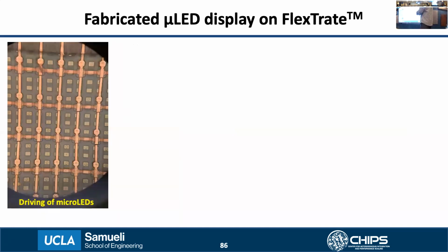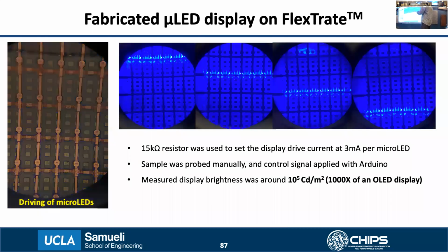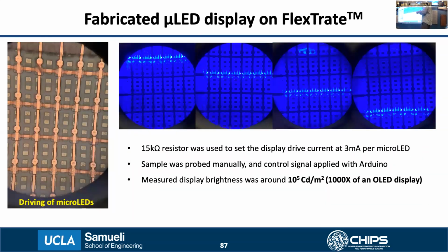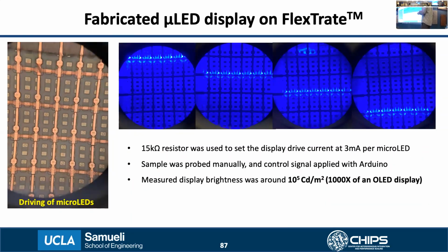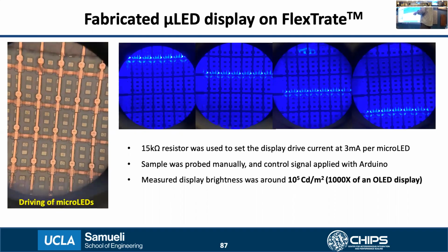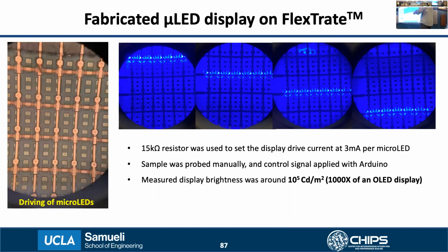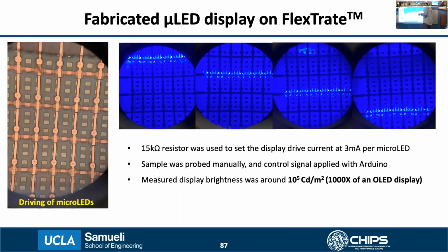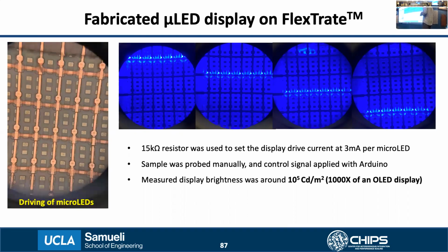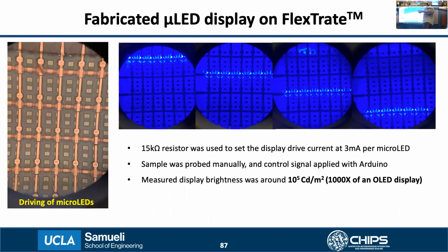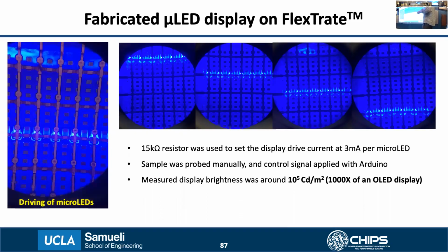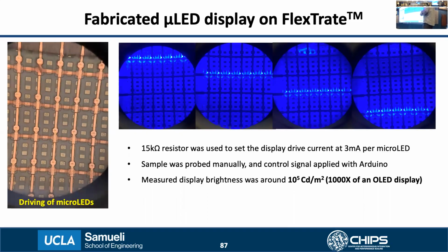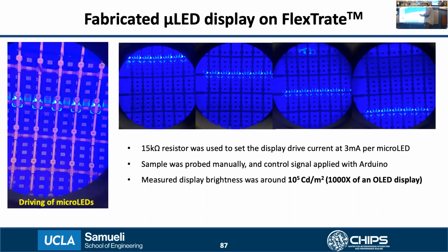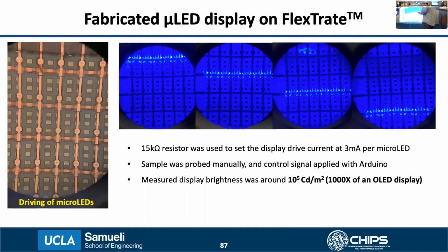Okay. So here you see a video of the display operating in scan mode, where the micro LEDs are being driven by the display driver ICs. For this sample, the control signals as well as the data for the ICs were provided through a probe station, through an Arduino setup. The display brightness was measured using a luminance meter to be around 10 to the power 5 candelas per square meter, which is around 1,000 times that of a similar OLED display.